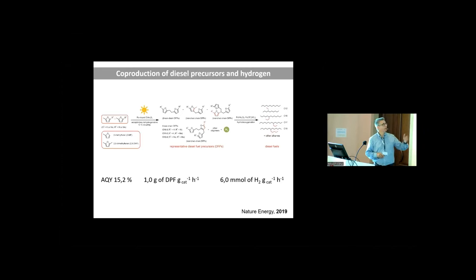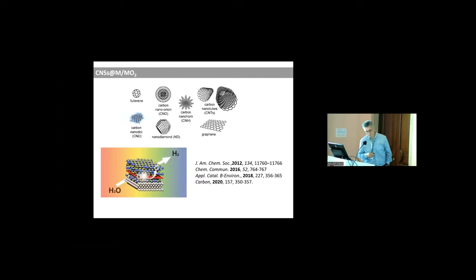Ruthenium is inserted into the lattice of this material. It's quite stable. We have performed operando studies at the synchrotron, using a high power laser to simulate long aging, and we observe very tiny deactivation due to some ruthenium going out from the material, forming very small ruthenium nanoparticles. We have a new generation of photocatalysts that is performing much, much better now.